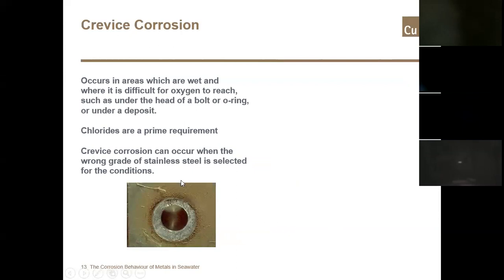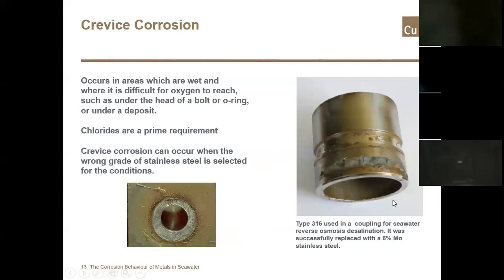You can see from the image on screen at the moment an area that's been sealed by an O-ring or a nut in a confined area and suffered crevice corrosion. Or we have an image here where 316 has been used for a coupling, and where the O-ring sat, there's been some crevice corrosion. Basically, this issue was cured by replacing the 316 with a 6% moly stainless steel, that then removed the tendency for crevice corrosion.